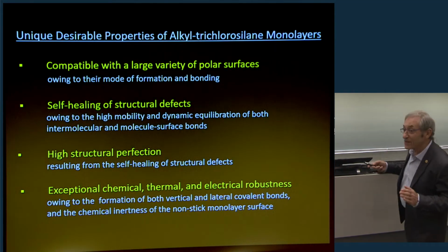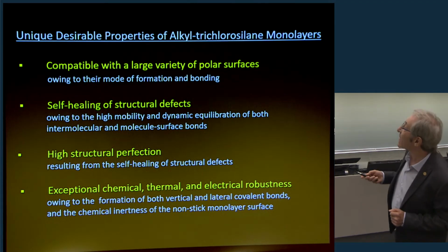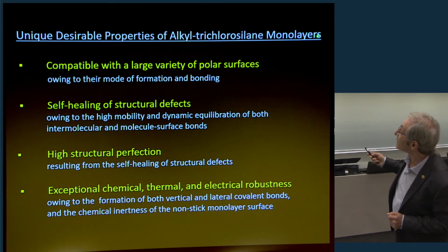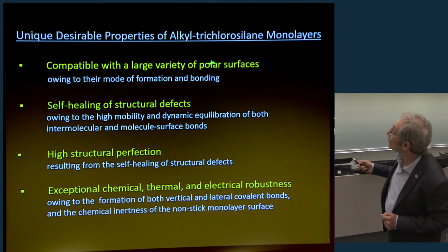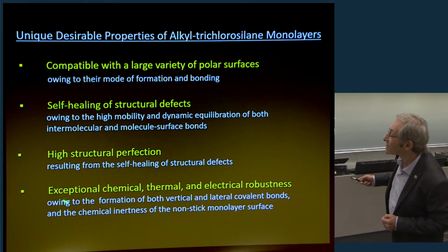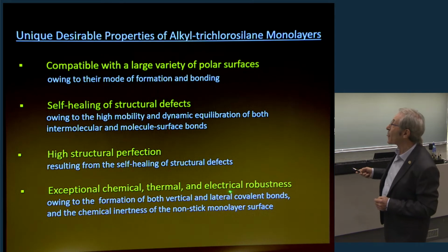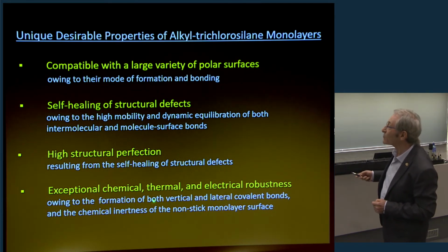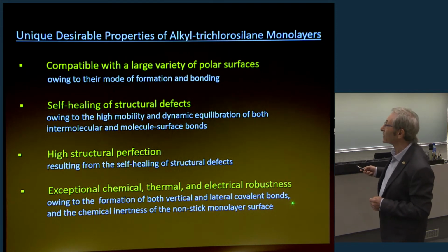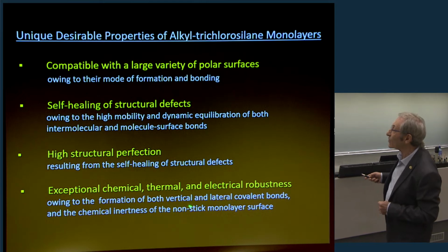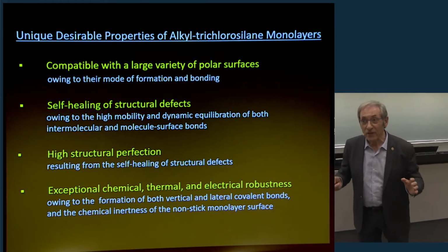Okay. So to summarize to this point, these are the unique, desirable properties of alkyltrichlorosilane monolayers: compatibility with a large variety of polar surfaces owing to their mode of formation and bonding; self-healing of structural defects owing to the high mobility and dynamic equilibration of both intermolecular and molecule-to-surface bonds; high structural perfection resulting from the self-healing of structural defects; and exceptional chemical, thermal and electrical robustness owing to the formation of both vertical and lateral covalent bonds and the chemical inertness of the non-stick monolayer surface. So these are very important properties.